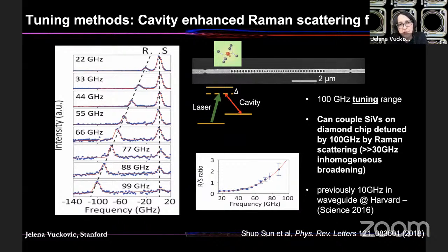For diamond color centers, here I'm showing the result for silicon vacancies, but of course this works also for tin vacancies. We have developed cavity-enhanced Raman scattering from a single silicon vacancy. This is the work done by my former postdoc, Shuo Sun, who is now at JILA in Boulder, starting his own group. The idea is that in order to compensate for the inhomogeneous broadening, you can drive your color center off-resonantly with a laser. You can change the detuning from the excited state transition and then perform Raman scattering into some optical mode. By changing the detuning of your driving laser, you can also change the frequency of the Raman scattered photon. And of course, for atomic physicists, this is nothing new. This is the type of excitation that is performed on lambda systems all the time.